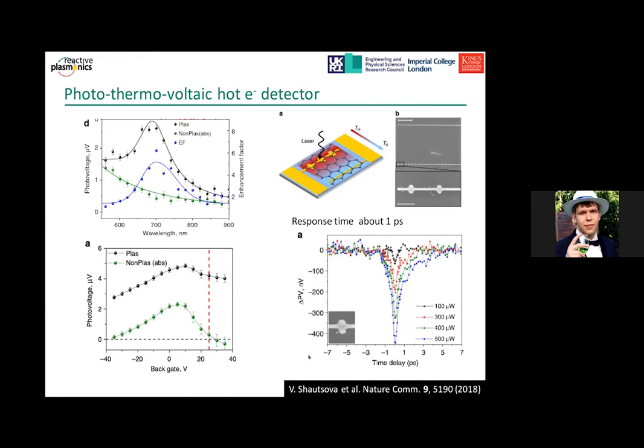Finally, we measured the speed of this detector, how fast it can react, by using a modification of the pump-probe setup. It shows that the detector mostly recovers within the picosecond time scale, which means it can be used up to the terahertz frequency range, which is not very common for photodetectors and is definitely advantageous in the field.